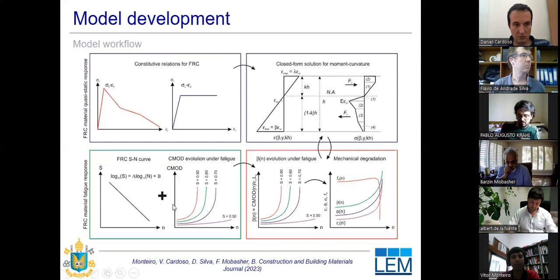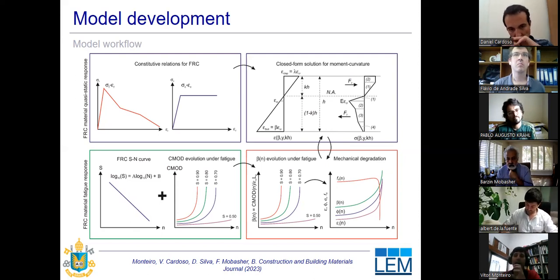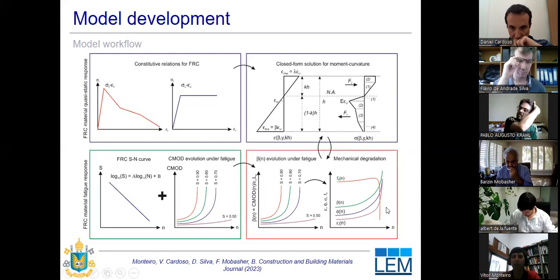Then we need to verify how the CMOD evolves along the fatigue useful life of the material. So we need to have an empirical equation. We can correlate the CMOD as a function of the number of cycles and also as a function of the applied load level of the test or the structure. After we know how the CMOD evolves, we can parameterize how the CMOD values change along the fatigue life and use the closed form solutions to calculate the other mechanical parameters that we need, such as the tensile strain and the flexural residual strain, and how they evolve along the fatigue test or the fatigue useful life of the material.